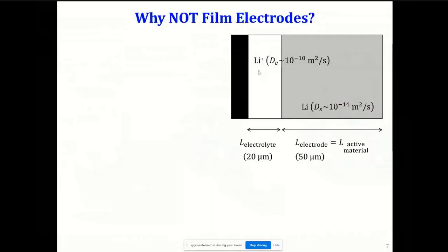With that, let me get to the first part, which is, let's first look at the simple film electrodes. So the situation would be something like that, where the black line is one of your electrodes, and what you want to design is the other electrode, which is gray, and it will be separated by electrolyte. Now what would happen is you would be diffusing lithium ions in between the two electrodes, and the corresponding diffusion length would be the thickness of the electrolyte.